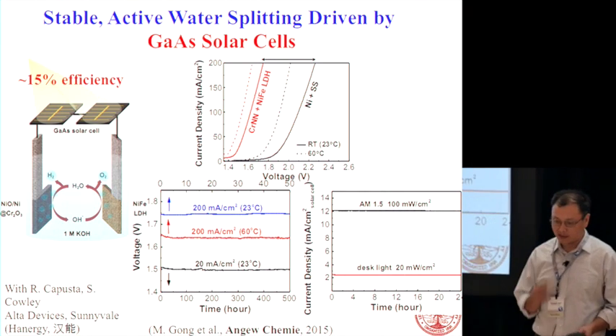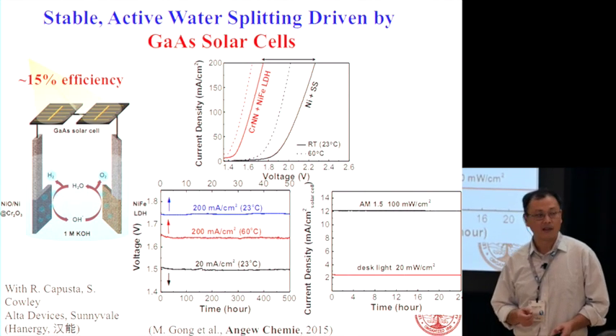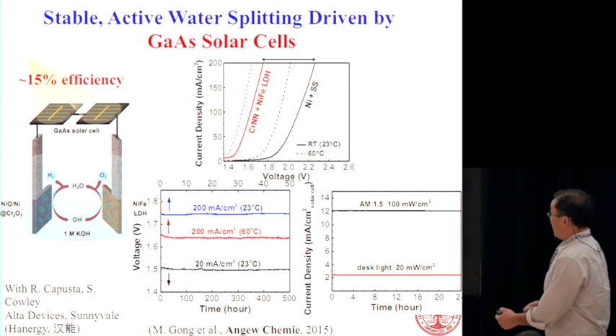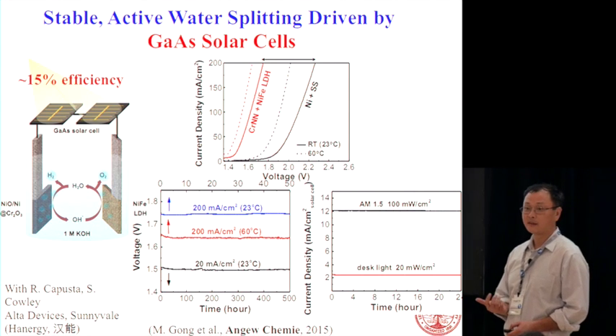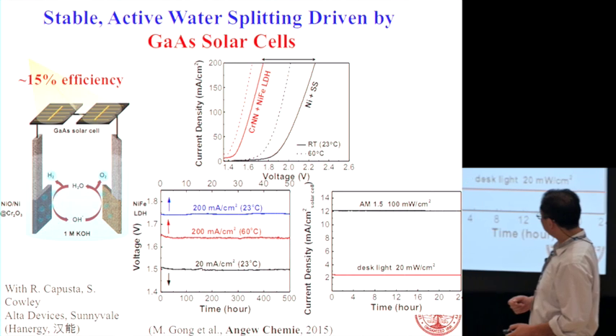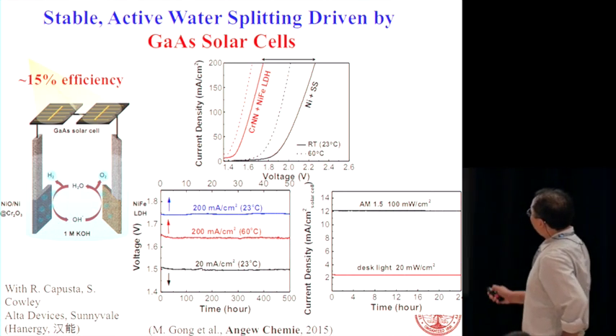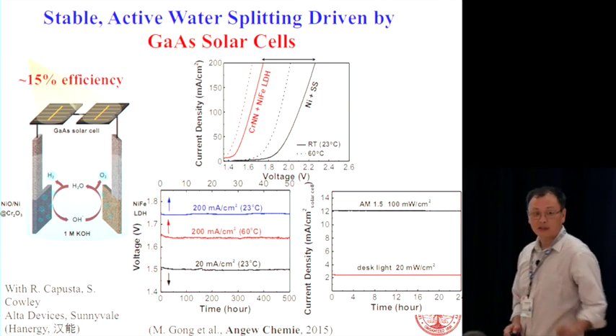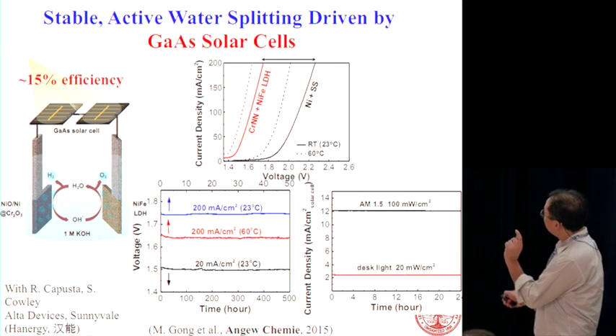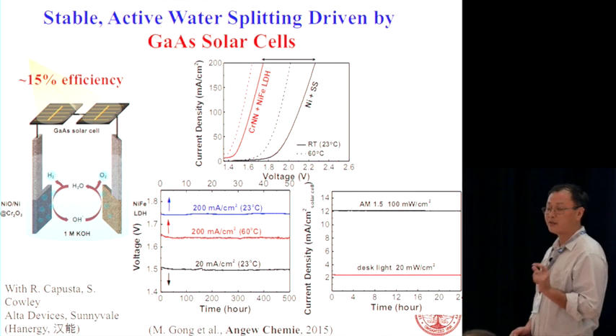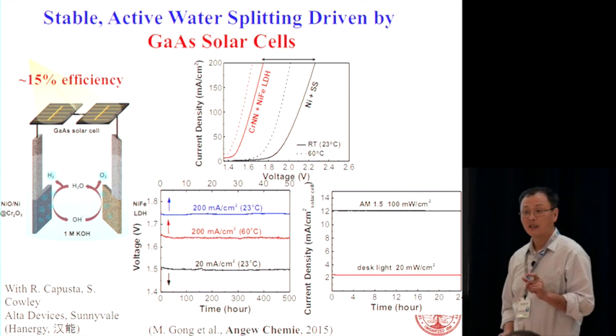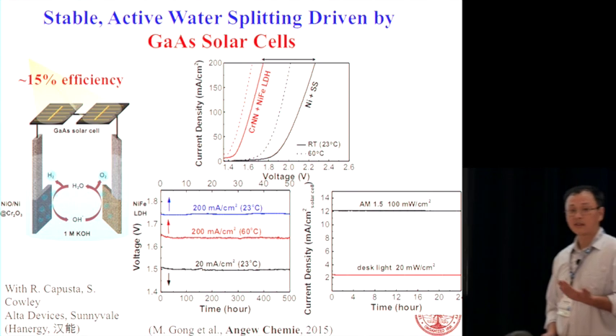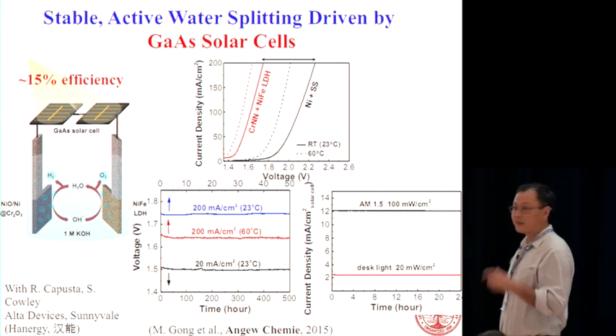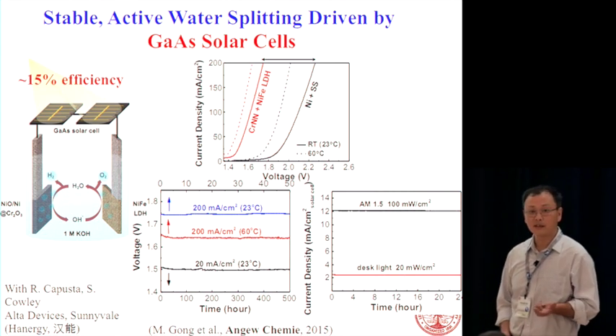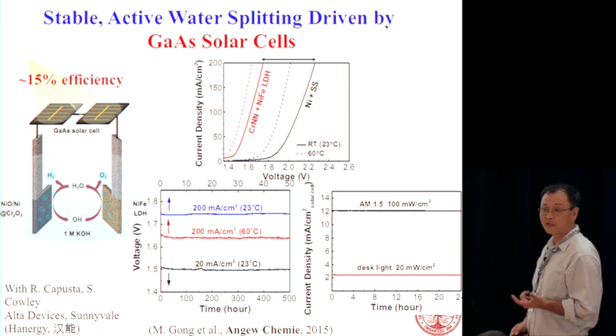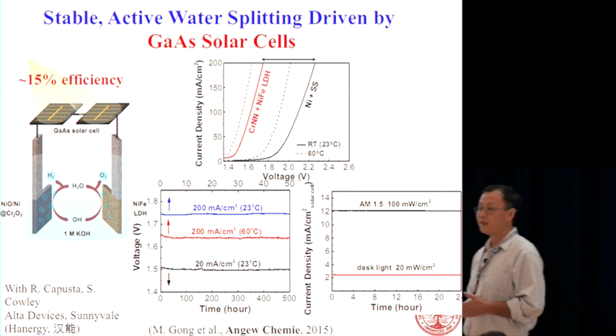And more recently, we went a step ahead and coupled it with a very good solar cell, a gallium arsenide solar cell, and we're able to achieve about 15% efficiency. So 15% of the sunlight is now going into producing hydrogen and oxygen. What I want to point out is this red curve here, the 2 electrodes we made. You can see we only need about 1.7 volts to produce 200 milliamps per square centimeter current. That's a current that you really need in industry to make these gases. If you don't use these catalysts and use conventional ones, nickel and stainless steel, you need about 2.4 volts. So that's a very large reduction in the voltage you need to produce the gases.